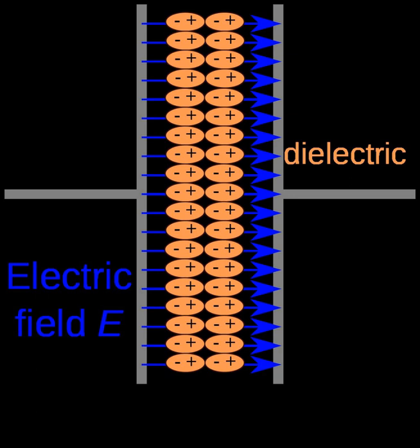Topic: Tunability. Tunable dielectrics are insulators whose ability to store electrical charge changes when a voltage is applied. Generally, strontium titanate (SrTiO3) is used for devices operating at low temperatures, while barium strontium titanate (Ba1-xSrxTiO3) substitutes for room temperature devices. Other potential materials include microwave dielectrics and carbon nanotube (CNT) composites.